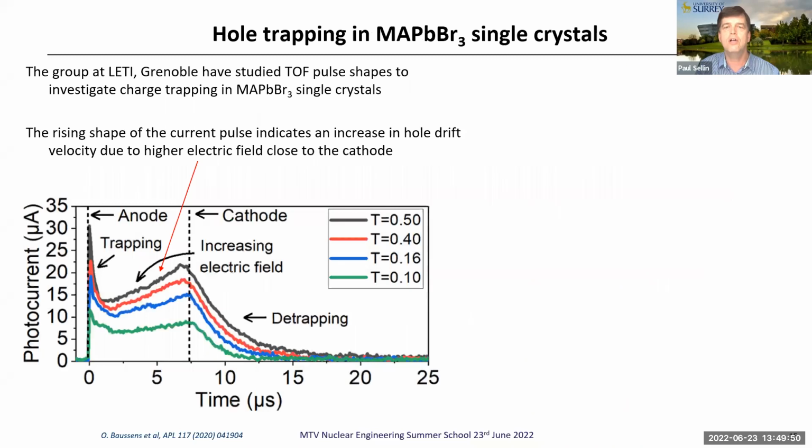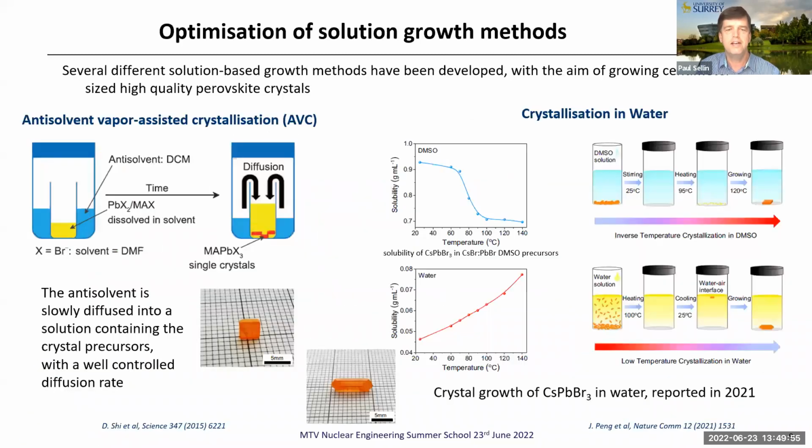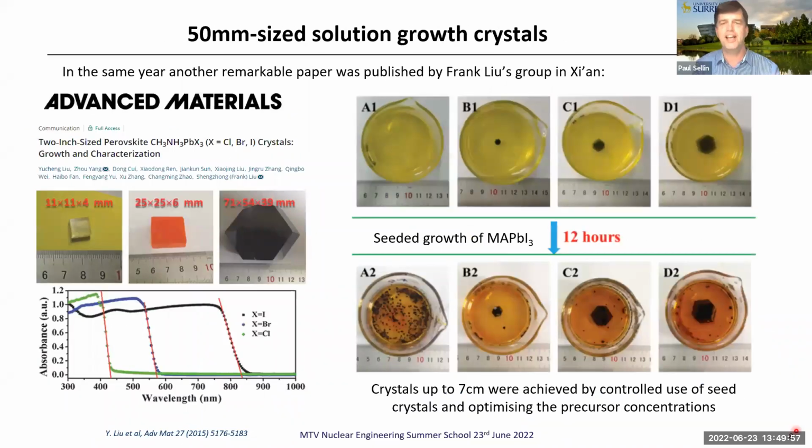As you can tell, the ones which are shown tend to be rather carefully selected. Certainly in our lab, you have to battle two problems here. One is spontaneous nucleation, as shown here, where suddenly the solution crystallizes in many different points. And then the other one is irregular growth.